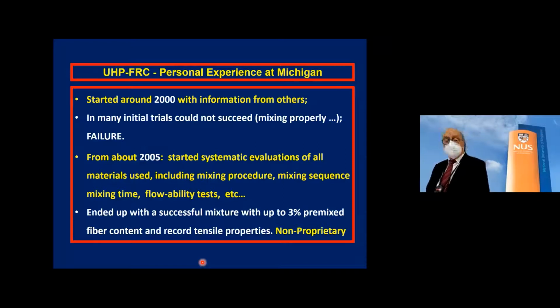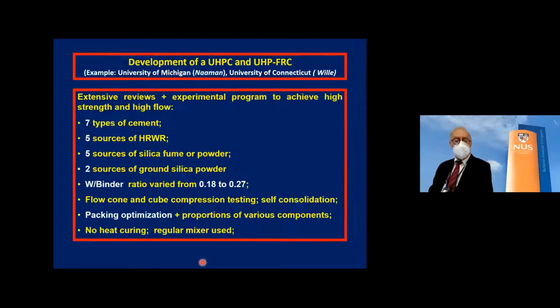I decided to start working with my student on ultra high performance concrete, and we ran a very systematic evaluation. Meaning we studied seven different types of cement, 5 sources of superplasticizer, 5 sources of silica fume, and so on, thousands of tests. And it took us about 3, 4, 5 years before we started getting some interesting results. So the study took about 10 years total. So at the end, we had some very nice results.